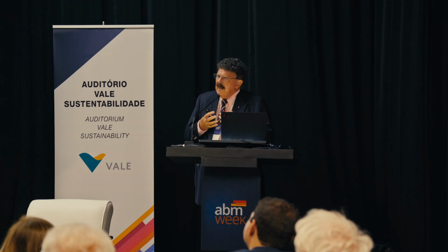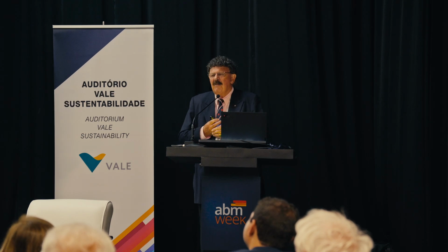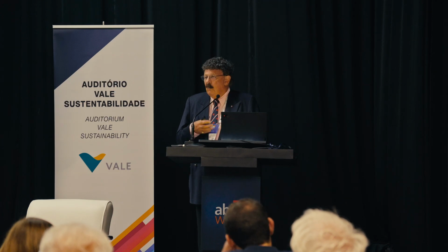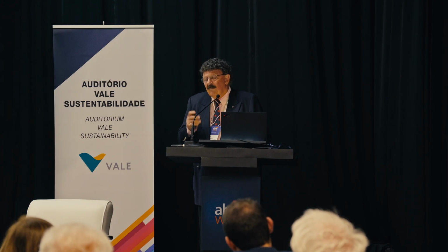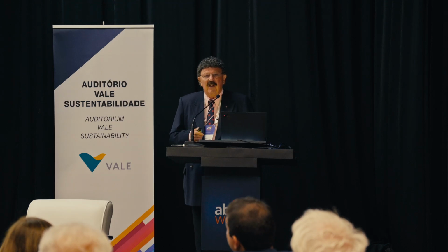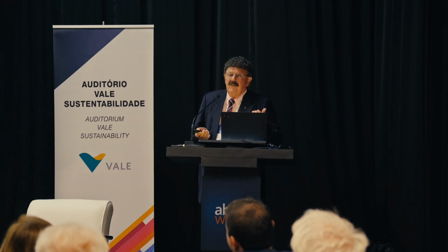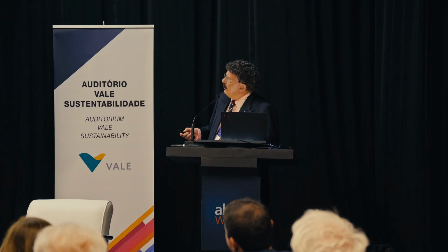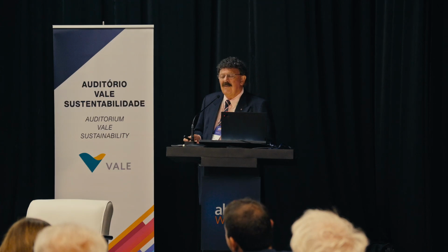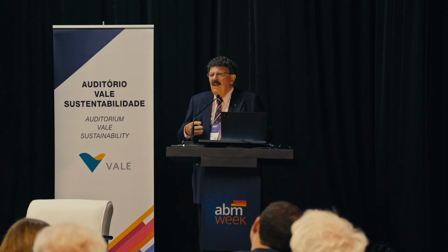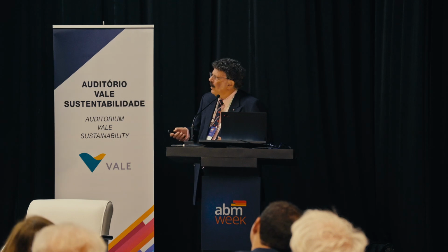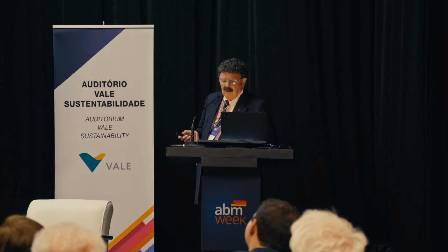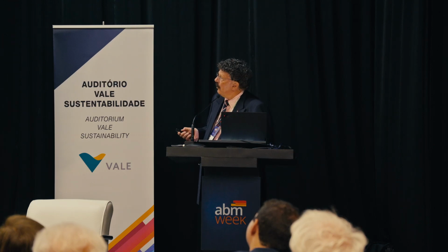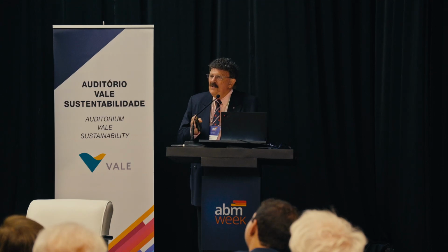So I think a false impression has been given to the community by a lot of people by doing everything in compression. We do toughness. Not many people look at toughness for some silly reason in these materials, and this is the toughness data, and as you can imagine, the toughness is terrible. This is this same superalloy. The toughness is below 10, and most of the time is below 5. Now compare that with the face-centered cubic structures that have toughnesses of 500 megapascals. Here we're down to really, really brittle materials. And of course, if you look at the fracture surfaces, you get a brittle fracture. This is intergranular fracture, and this is not unusual for these materials.